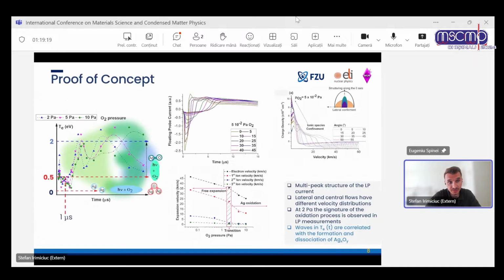which then again will affect the properties of the film. And then if we change the argon with oxygen, we can look at the oxidation, and we can check the oxidation with a simple Langmuir probe inside the plasma, just by seeing this modulated variation in the electron temperature this time. So electron temperature becomes important for the oxidation system, and this is something that we need to take into account later for more complicated systems.